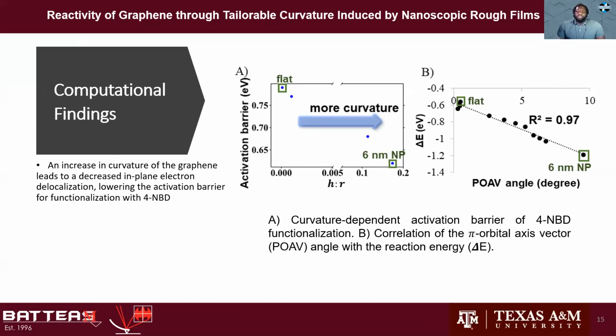We also developed a theoretical model based on the pi-orbital axis vector, POAV, method to quantify the effect of curvature on the orientation of the graphene 2pz orbital. We determined that the curvature affects the in-plane electron delocalization and increases the electron availability for out-of-plane functionalization, shown in figure B, indicating an increased thermodynamic preference for 4-NBD reactivity to greater curved graphene.